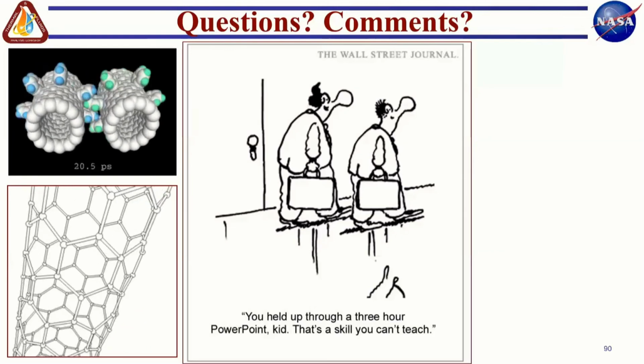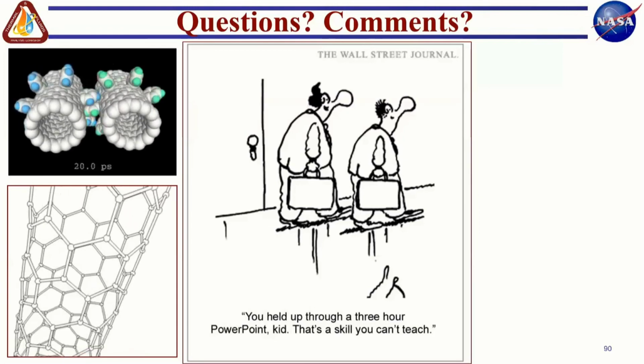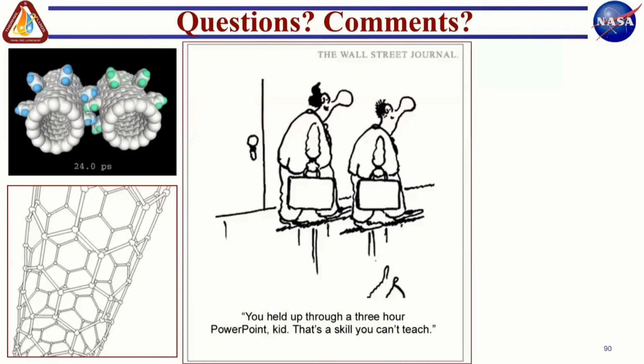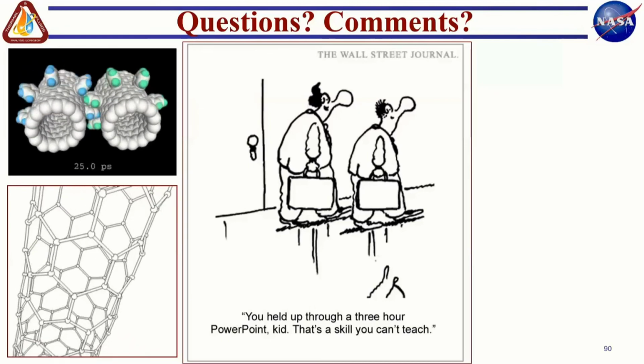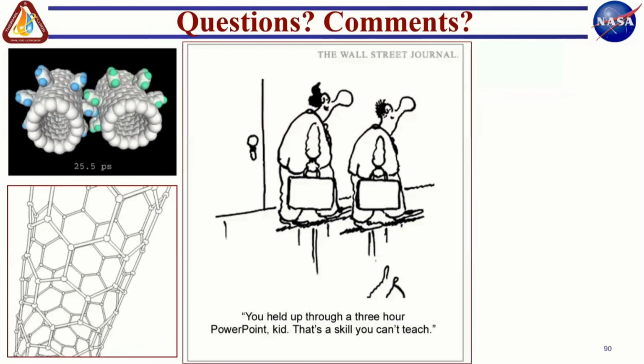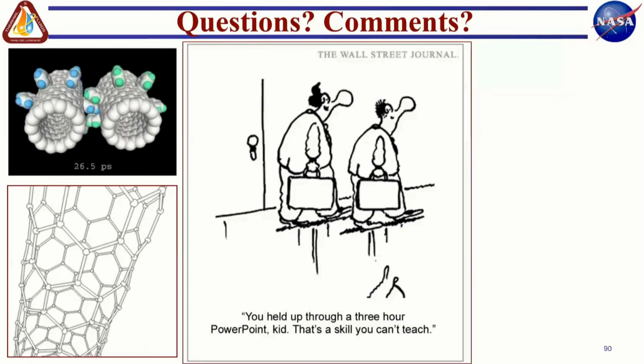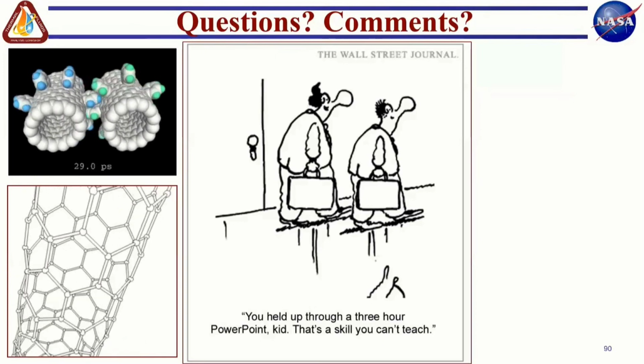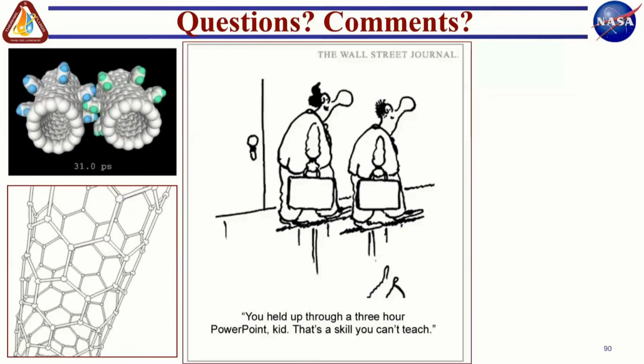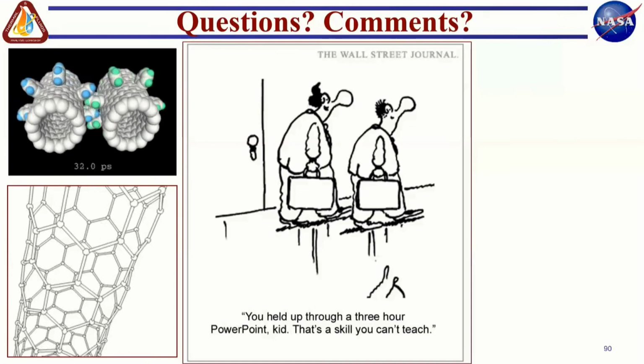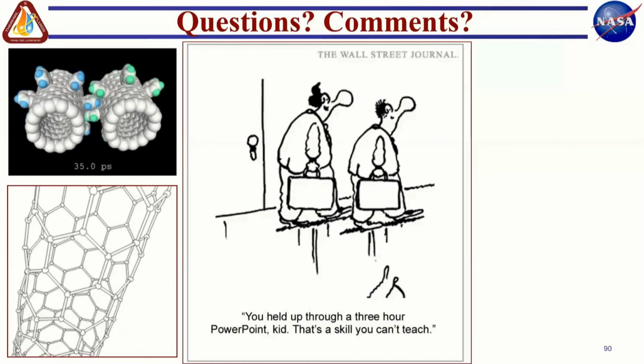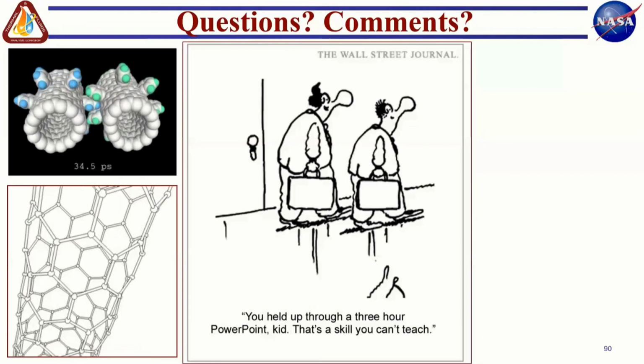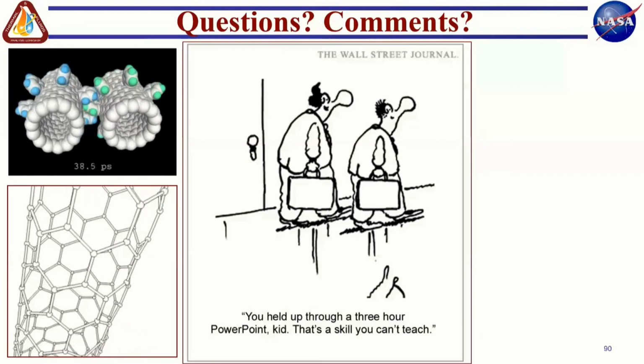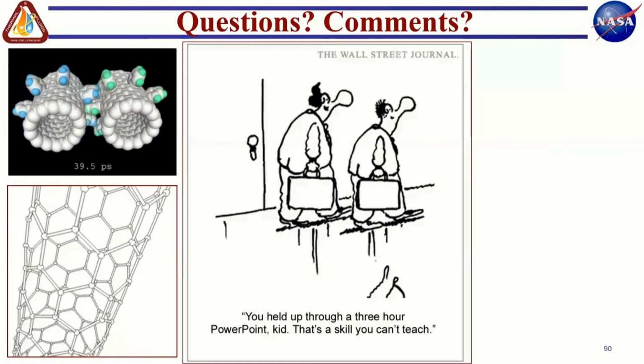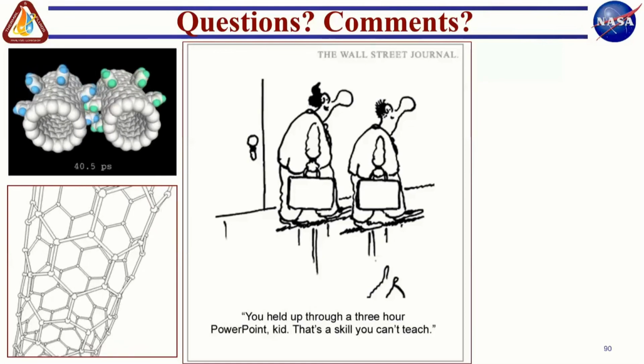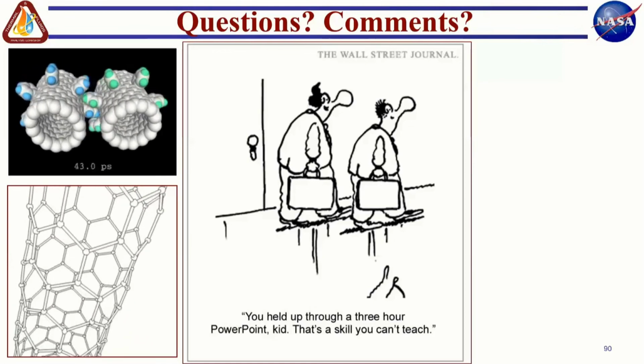Now, coming to the size of the nanoparticles, there is this other conundrum from a heat transfer design point of view. So the smaller you make the nanoparticles, the more ice layer you get per unit mass of the nanoparticles, because you have more surface area. On the other hand, the more surface area you have, more Kapitza resistance you have. So that's a trade-off. So if I'm designing a coolant and my objective is to maximize the thermal conductivity of the mixture, then the sweet spot is somewhere between 50 and 100 nanometers. This was actually predicted by Pat Phelan's group at Arizona State, and that model works beautifully. That shows how the Kapitza resistance changes and how that affects the net thermal conductivity of the nanofluid.